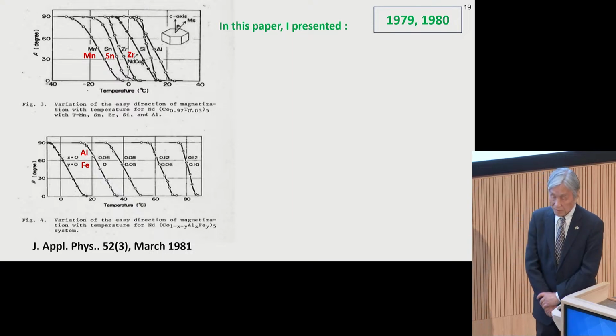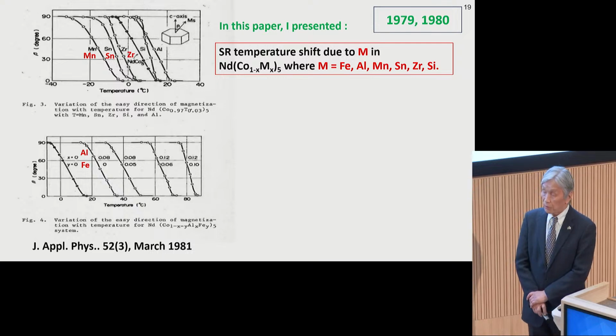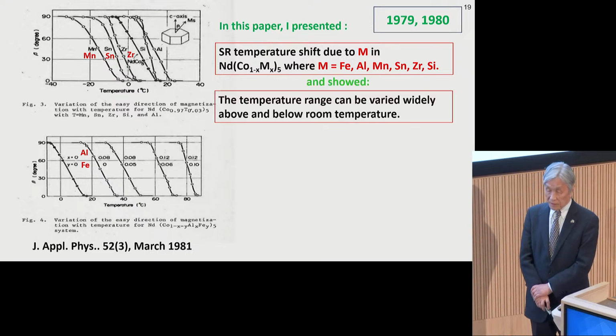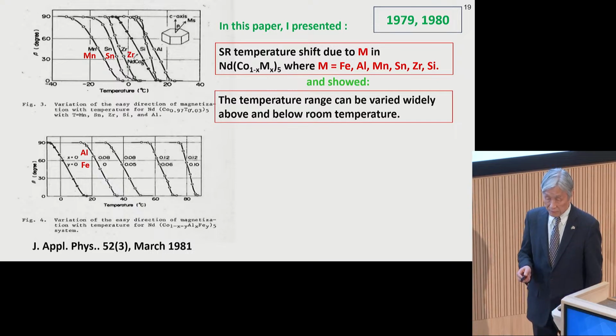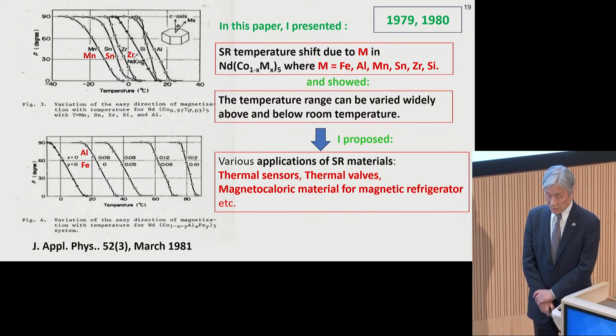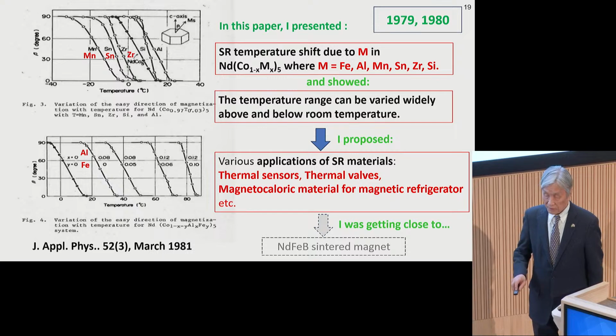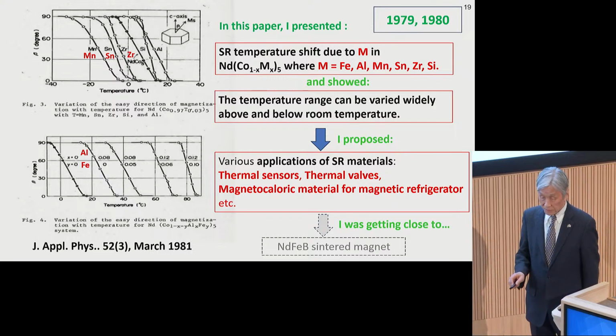And in this paper, I presented SR, spin reorientation temperature shift due to M, additive element in neodymium cobalt M5, where M is iron, aluminum, manganese, tin, zirconium, silicon, and showed the temperature range can be varied widely above and below room temperature. And I proposed various applications of SR materials, such as thermal sensors, thermal valves, magnetocaloric material for magnetic refrigerator. Please note that I was getting close to neodymium iron boron sintered magnet, because this SR material is also produced by sintering.